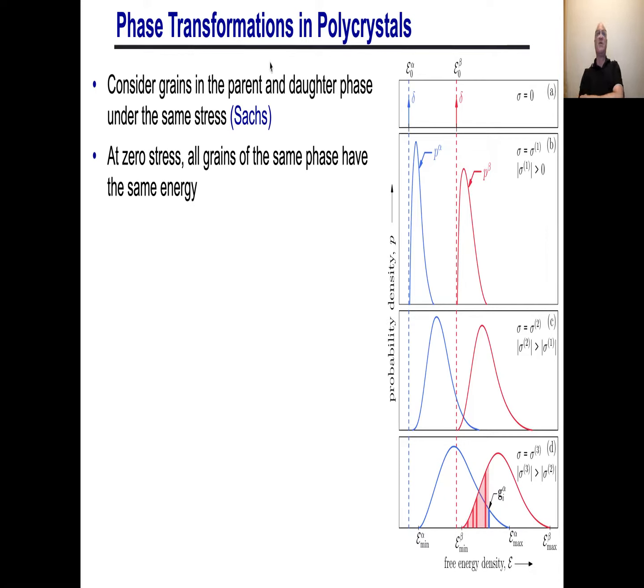Okay, phase transformations in polycrystals. If I take a polycrystalline material and I look at the free energy of every grain under zero stress, well, the alpha phase and the beta phase have the same energy. So these are just two delta functions, independent of the orientation of the grain, because its stress is zero. Now, if I apply just some arbitrary stress, then the distribution of energies that you would get for the two phases now starts to spread, because for an arbitrary stress, different crystals are oriented different ways. And so I have to look at the whole rotation of the elastic constant tensor. And so in principle, I could go over all SO(3).